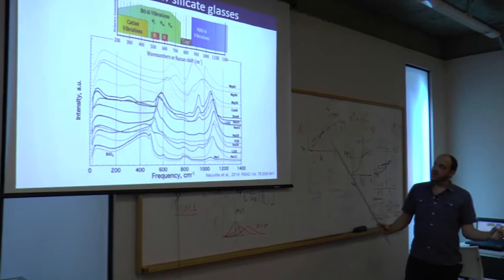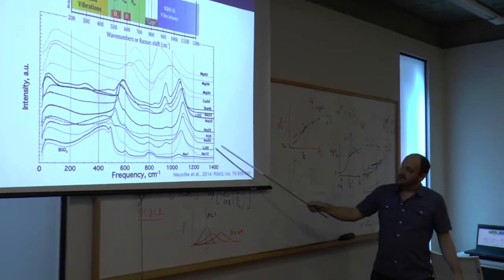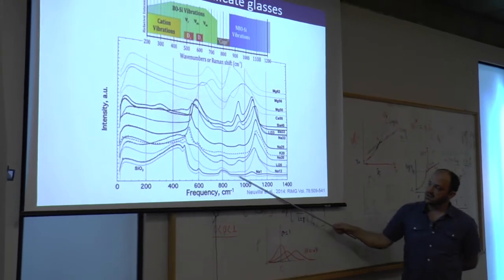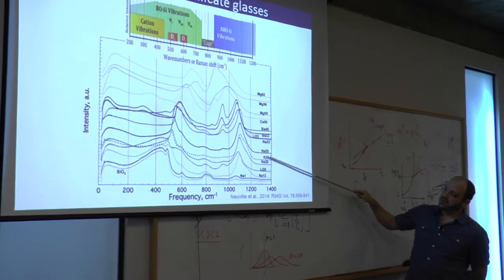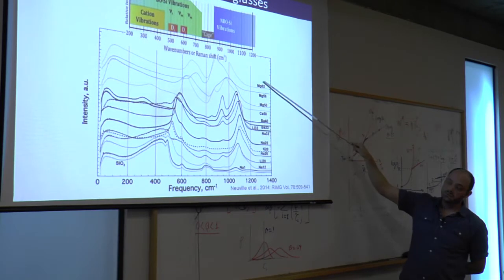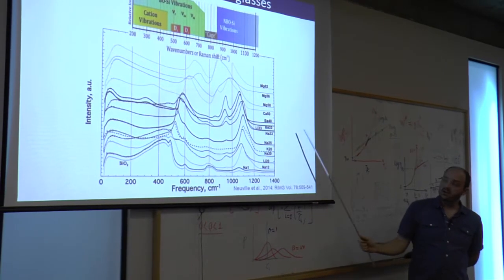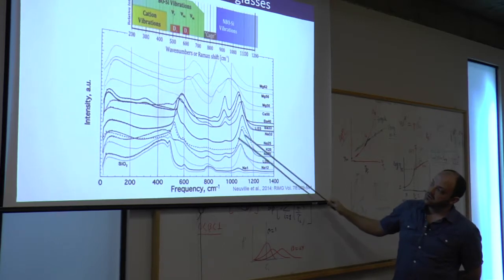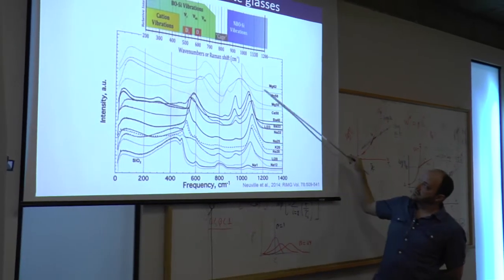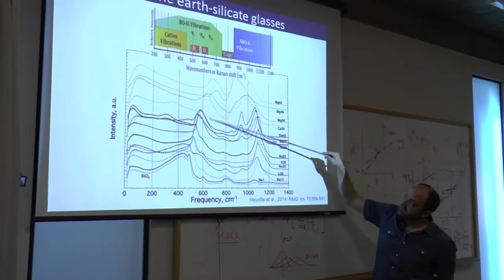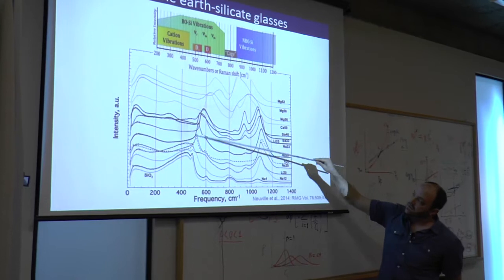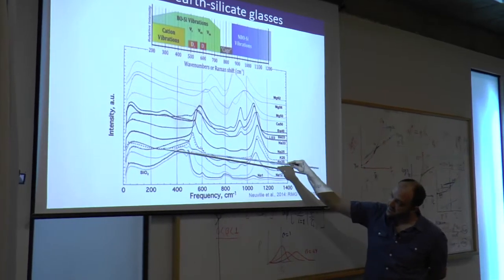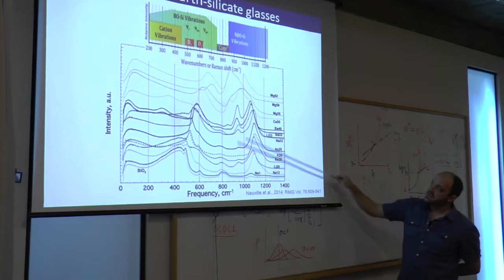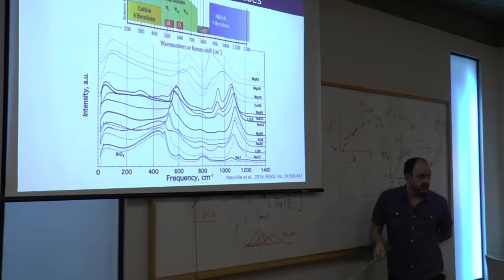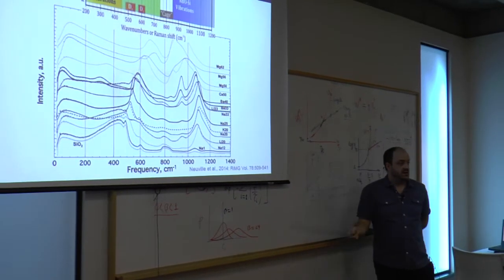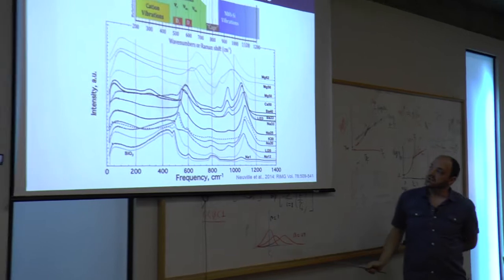This is just a summary figure. Don't worry too much about it in terms of trying to pick things out, but here's silica-rich compositions at the bottom. Here's sodium, lithium, potassium glasses, barium, calcium, magnesium glasses. All the dominant alkaline and alkaline earth silicates share some similar features. As you get to higher modifier contents, as I mentioned, these bridging oxygen vibrations move to higher wave numbers. As you go to silica-rich, they tend to have this tail towards the low frequency end. And we can see that the Q speciations has some pretty strong variations as you go from Q3s and Q2s down to Q1s and Q0s.